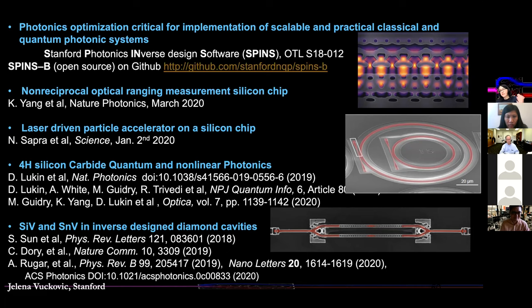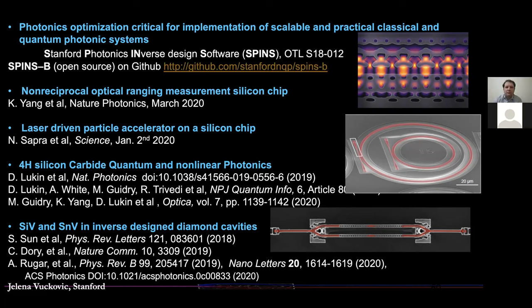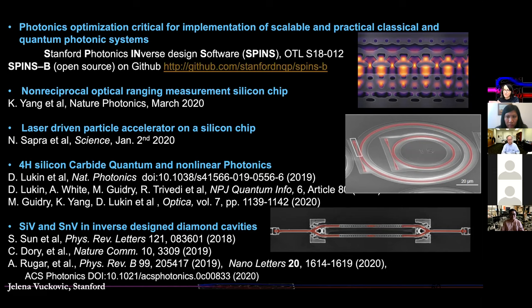And then that material would be thinned down and made into silicon carbide on insulator. Once we do that, and we have these high quality emitters with the right dipole polarization in the resonators, which is in-plane polarization, I think we should be able to see strong coupling. That was not the case before. The experiments that I showed with large enhancement were so-called V1 prime transitions in silicon vacancy in silicon carbide, which are in-plane polarized, but they are known not to be very good. And V2 is TM polarized, right? So if you start from a different cut of material, then your V2 line would be in-plane polarized and coupled to the cavity, and then you can have strong coupling.